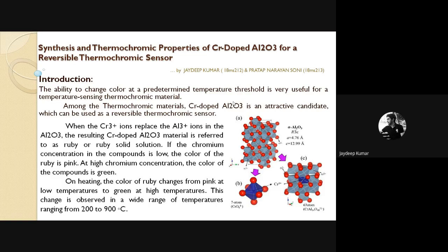Vanadium oxide is also good, but it has a small transition temperature, just 68 degrees centigrade, and it can be used only till the temperature of 200 degrees centigrade. So this was the best example till now that can be used at least till 900 degrees centigrade.